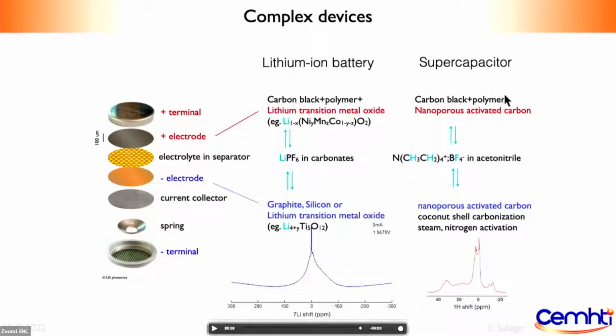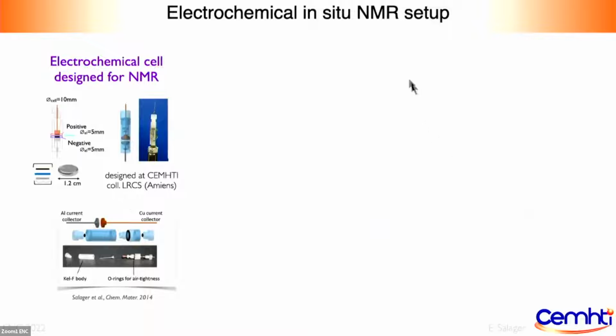For supercapacitors, it's a bit different. The two electrodes are the same, it's just their polarization that is different, and it's just the organization of the ions. So again, you get lots of superposing peaks and also some shifts that come from magnetic susceptibility changes. So what we aimed at was to use the imaging capabilities of NMR to disentangle these spectra and be able to tell things about the ions in the positive and the negative electrode. The setup that we designed in our lab was with this kind of electrochemical cell.